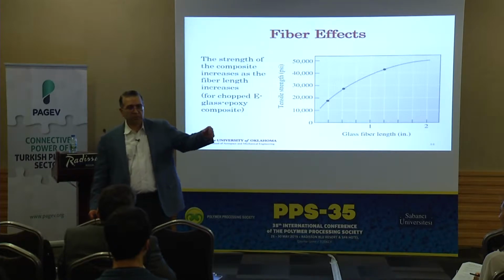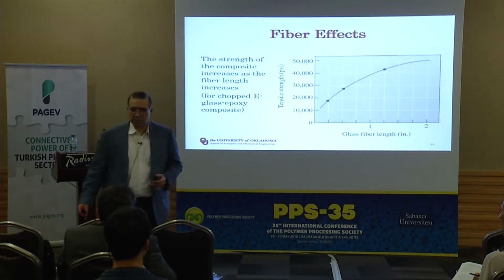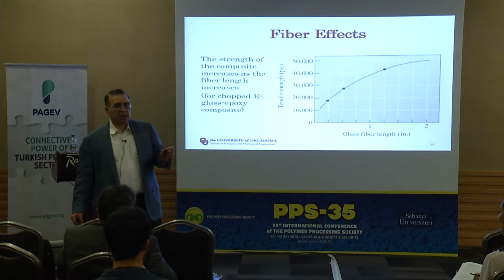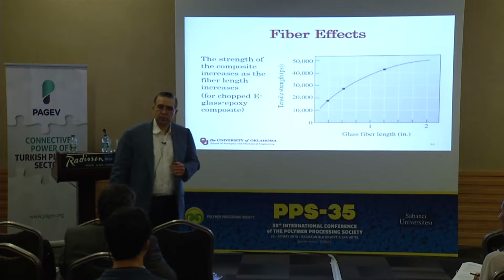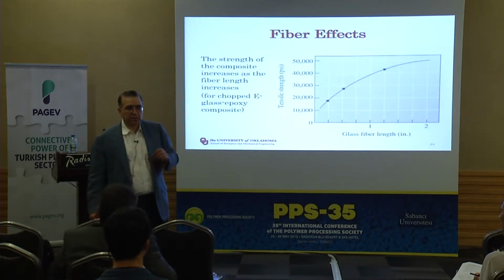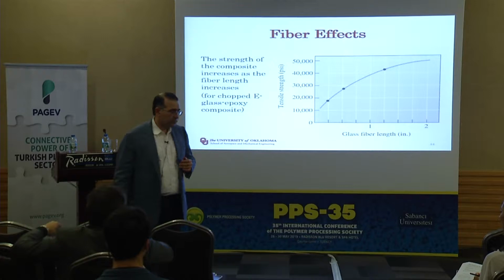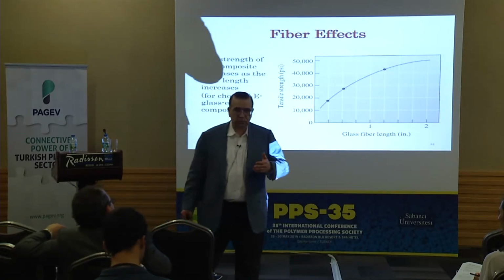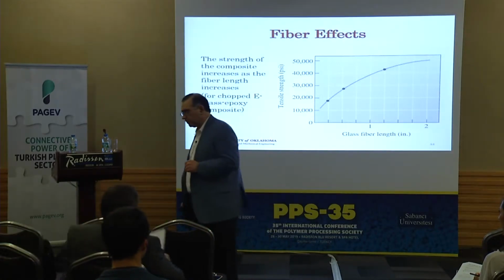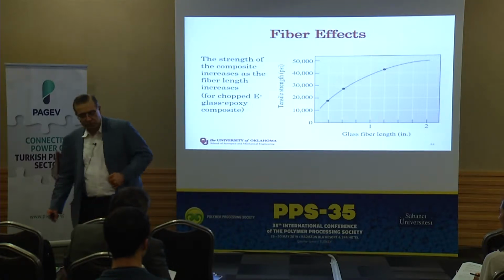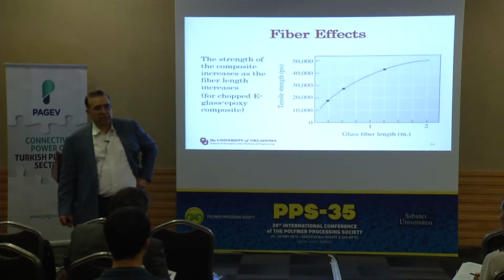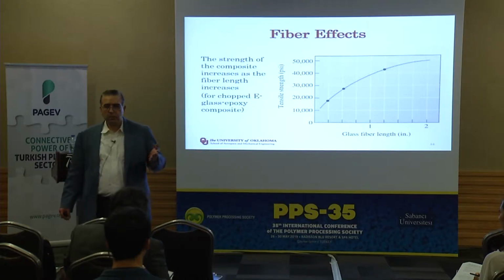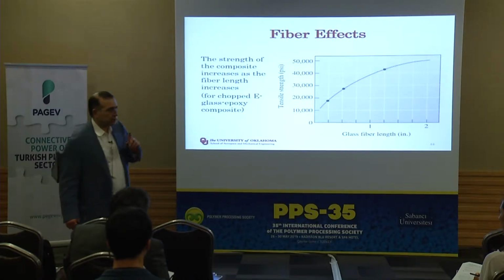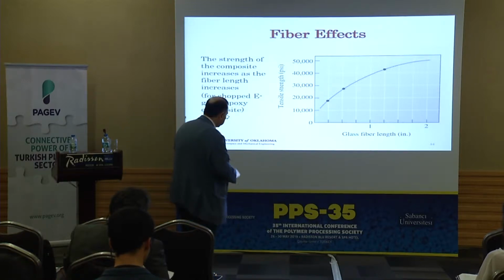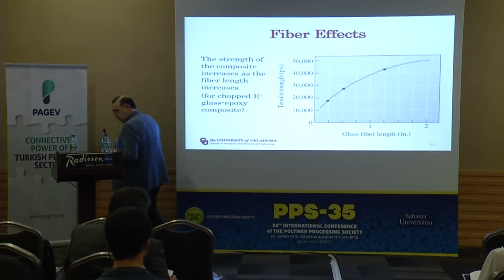In injection molding, the fiber length is maybe 200 microns, so 0.2 millimeter. Okay? And the fiber diameter is 15 microns. So your fiber aspect ratio is another important property for discontinuous fibers. Fiber aspect ratio might be around 30 to 50 to 80. Okay? So that's also an important property, fiber aspect ratio.